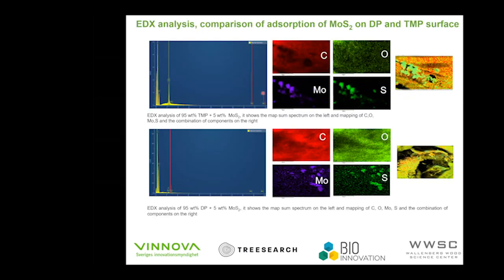We said, okay, lignin has some aromatic parts, so molybdenum disulfide should have a better interaction with the TMP than the DP. So here you can see that we have a very high intensity peak of molybdenum in the TMP composites. But here we have a very low intensity of molybdenum in the DP-based samples, and our theory was somehow confirmed. And what is the main conclusion about this first project? Molybdenum disulfide has potential as a lubricant for TMP fibers and forestry products in the future.